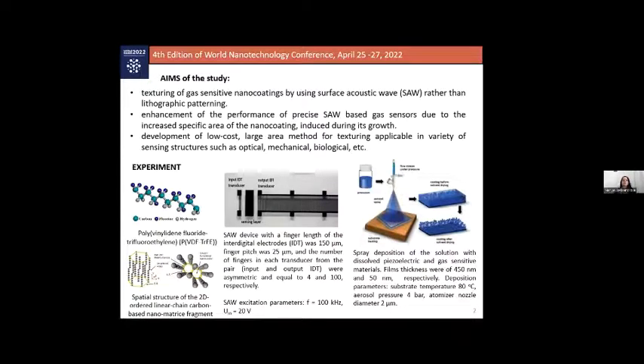So the aim of the study in the first place was to achieve texturing of the sensitive film, avoiding expensive techniques like lithographic patterning, only relying on the propagation of the acoustic wave. In this way, if the film is excited with the surface acoustic wave during growth, it is expected that there will be enhanced performance of the gas sensor because it is expected to induce an increased area of the nanocoating.